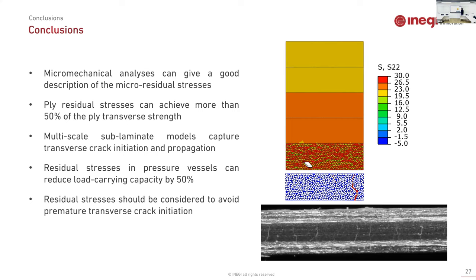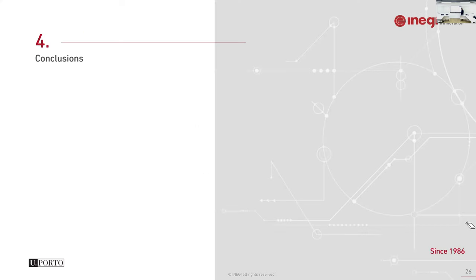Looking at the pressure vessel example, the transverse damage mode can reduce considerably the pressure load carrying capacity, of course. And unfortunately, residual stresses should be considered to avoid premature transverse crack initiation, as we can see in this example. Sorry.